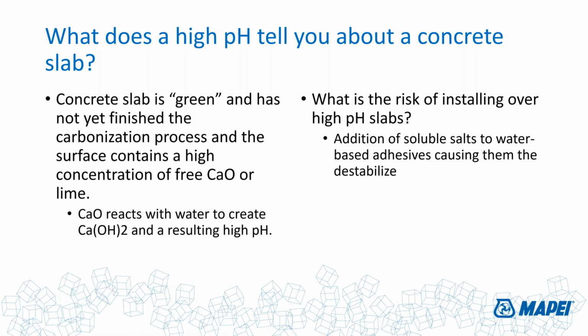So what does the high pH tell you about a concrete slab? Really what you're measuring at this point in time basically tells you how green it is, or how young it is, or whether there's been enough carbonation on the surface of the concrete to neutralize it. So a green concrete, as I mentioned before, has a very high pH. It hasn't had enough time to react with the carbon dioxide in the air to neutralize the surface. And we'll talk a little bit about carbonation here in a minute.